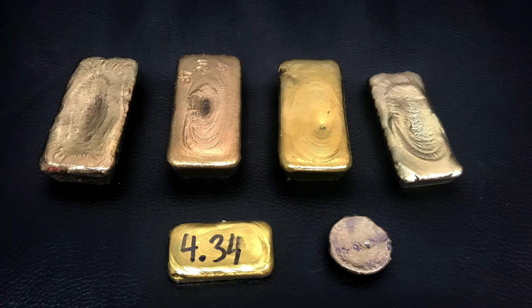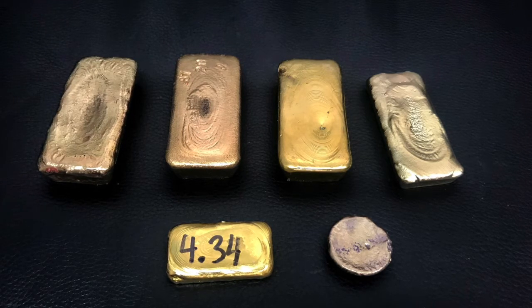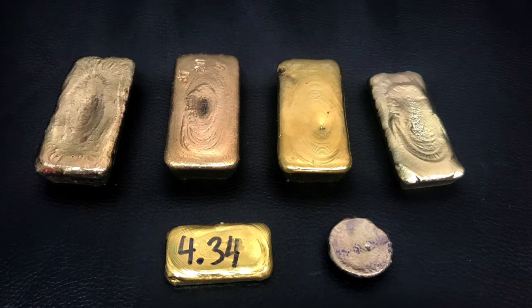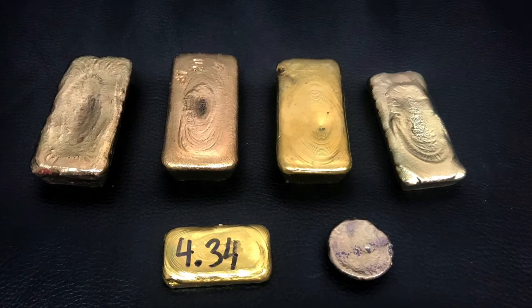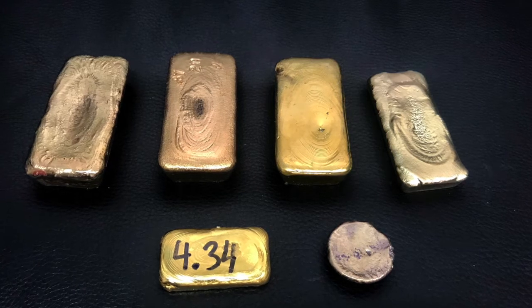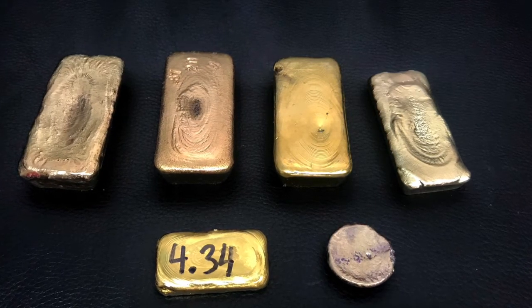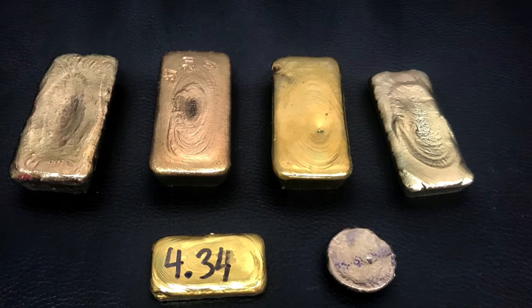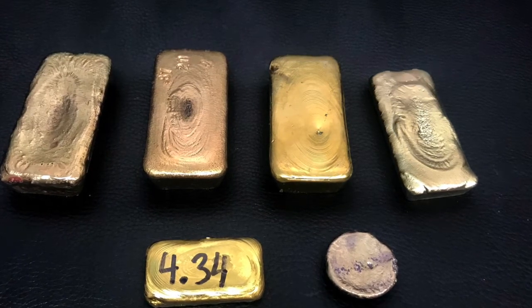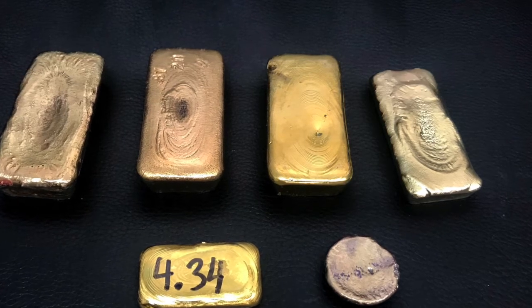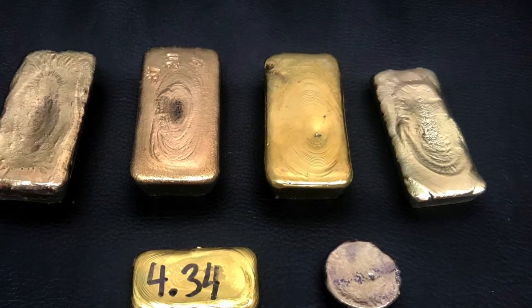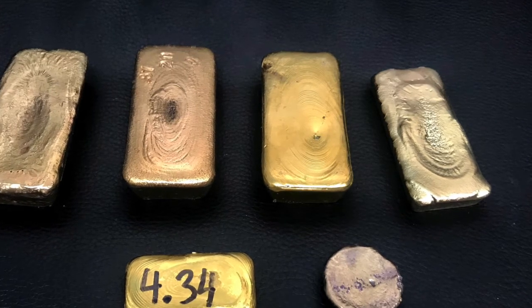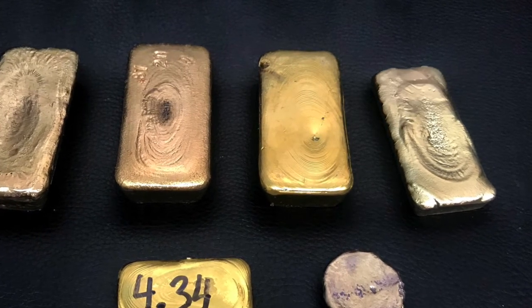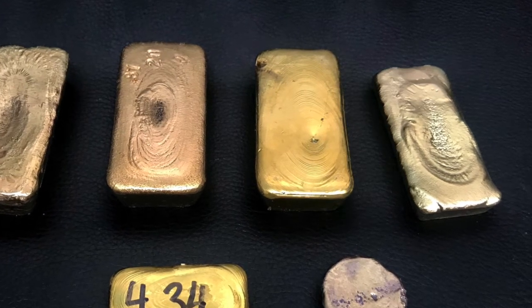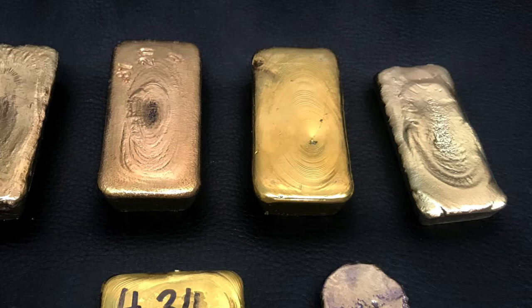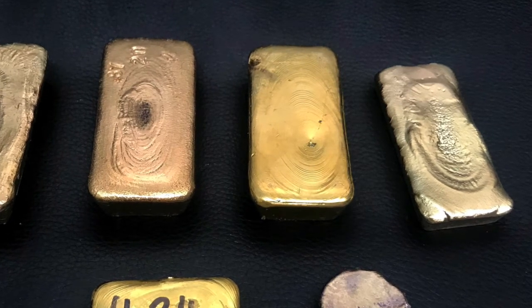Now, two of these bars, the one marked 4.34 ounces and the most yellow one, second from the right, are practically pure, and that's from just the nitric acid leach in the inquartation process. All of these could be refined further to the standard of 99.9% purity, 999 purity. But you wouldn't get any additional value from that in selling it to the buyer. They're quite happy to buy it at less purity than that.